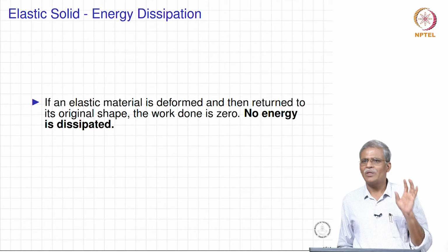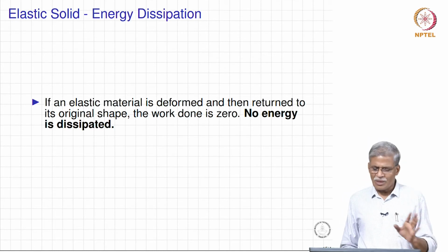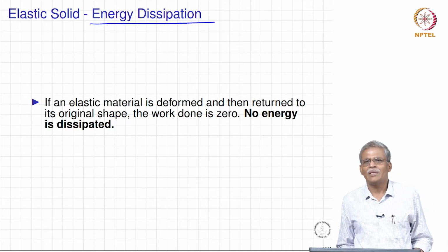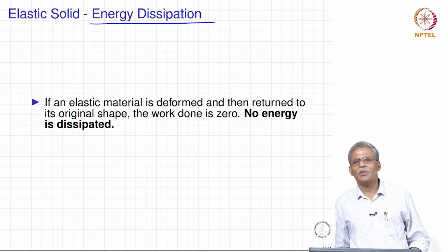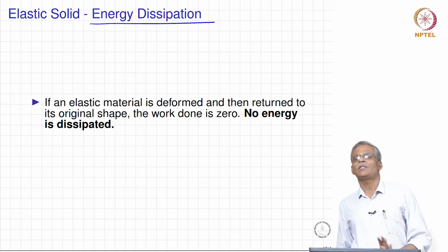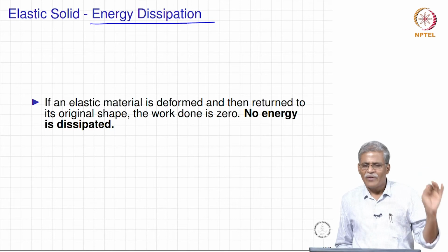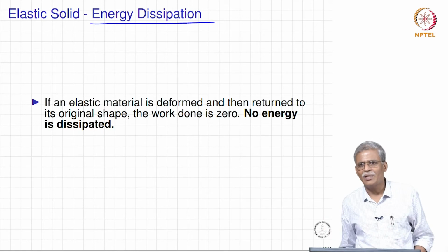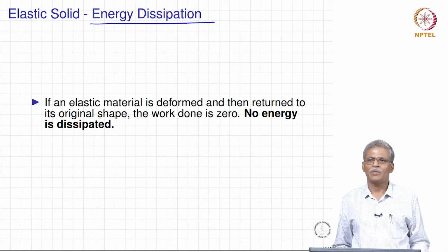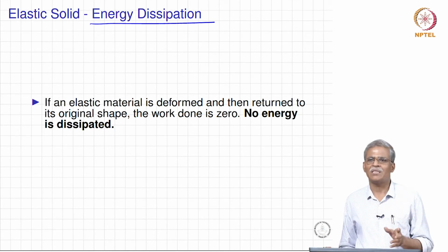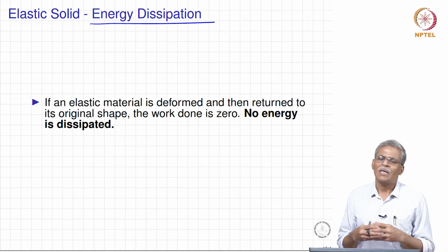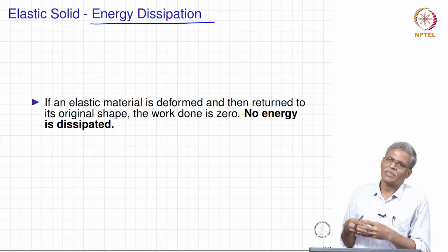So, it is always very useful to keep in mind what is called the energy dissipation. As far as bituminous materials are concerned, it is necessary to understand that some amount of energy is going to be dissipated whenever there is a vehicle passage in real life, be it in the case of rutting, which you must have heard many times during this lecture series, or in terms of fatigue damage. There is always going to be an energy dissipation, and the quantification of the energy dissipation gives us some reasonable and rigorous specification criteria.